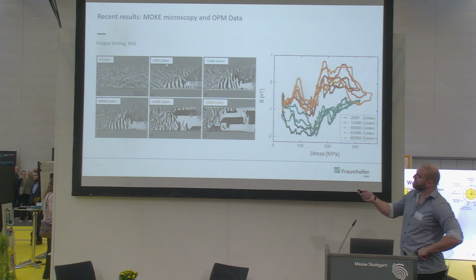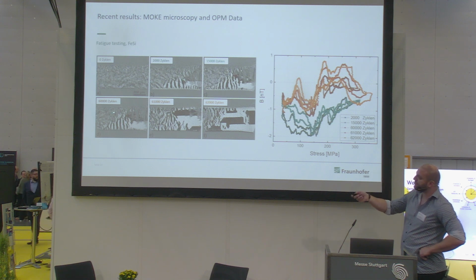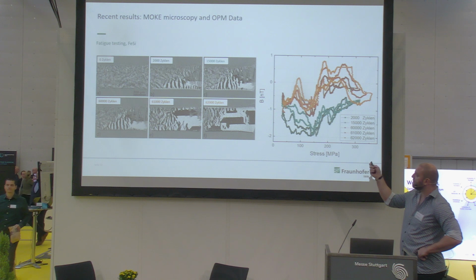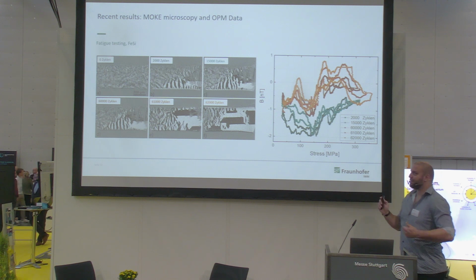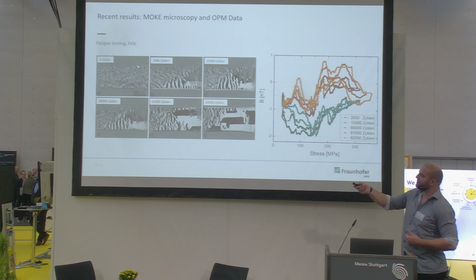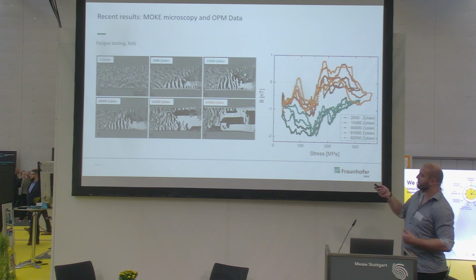If you have a look at the top 2 parts, these belong to the green curves, and the bottom 3 belong to the red curves. So now there's a difference happening. Most of the changes happen between 60,000 and 62,000 cycles. And in the OPM, we have the green curves, which go to 15,000 cycles, and most of the changes happen between 15,000 and 60,000.